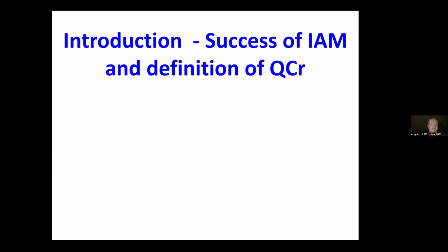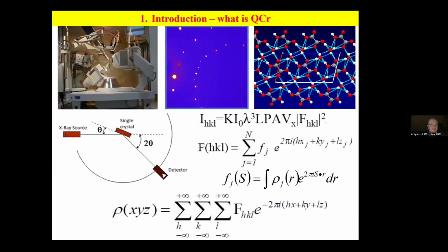So let us go to the first point. Ladies and gentlemen, let's begin with fundamentals, with the procedure of routine X-ray structural investigations. When proper single crystals are available, one can mount a piece on a goniometer head of a diffractometer and collect thousands of frames containing intensities of reflections, which are a function of several instrumental factors, which can relatively easily be taken care of, and the most important, which depend on the square of structure factors.